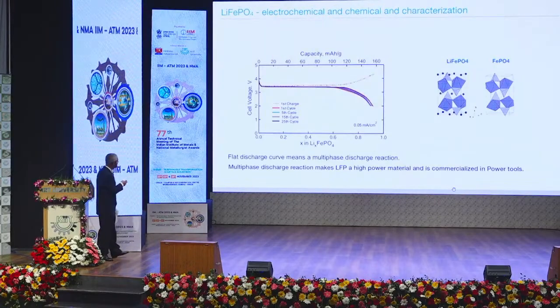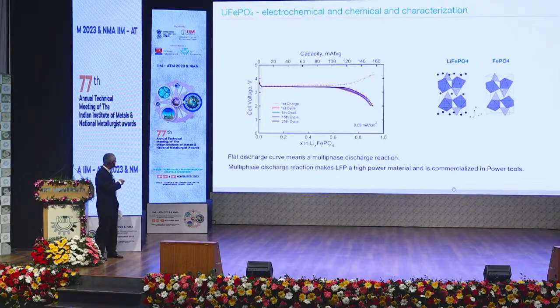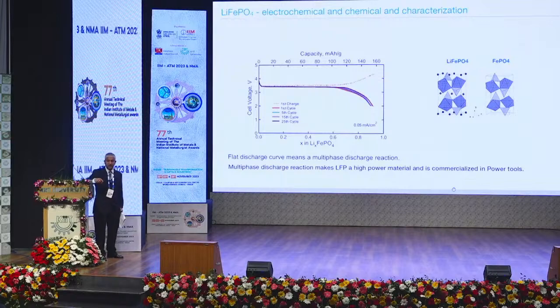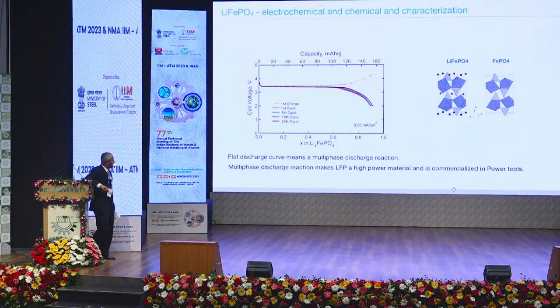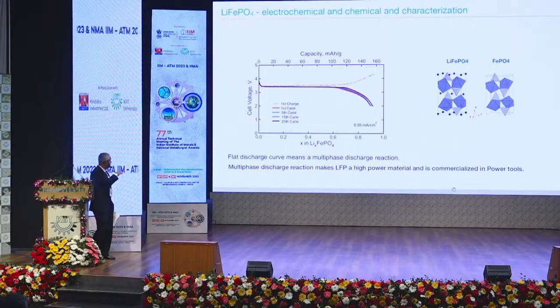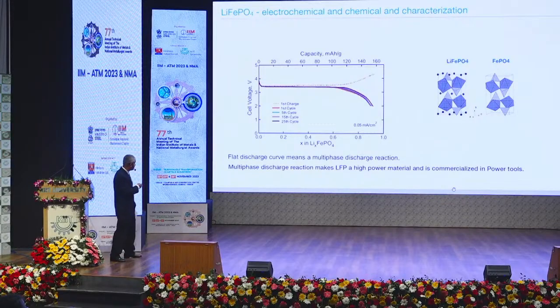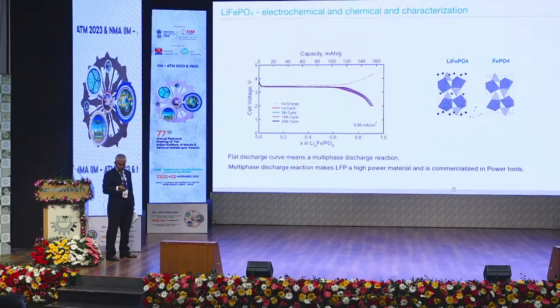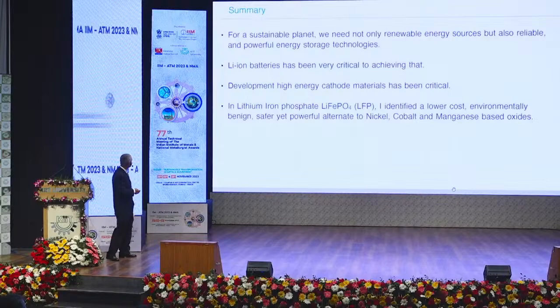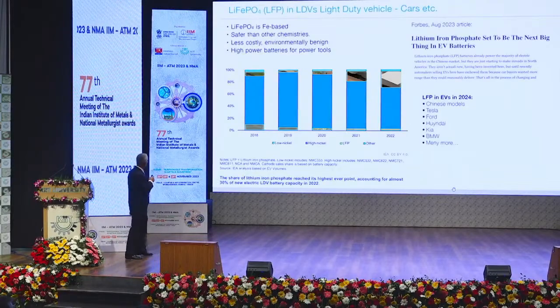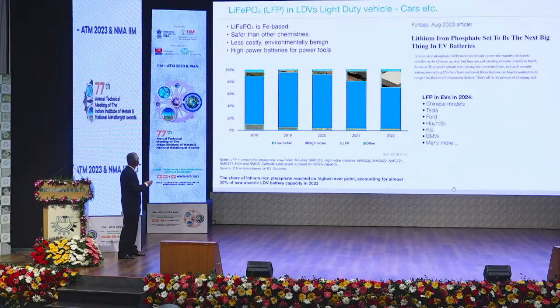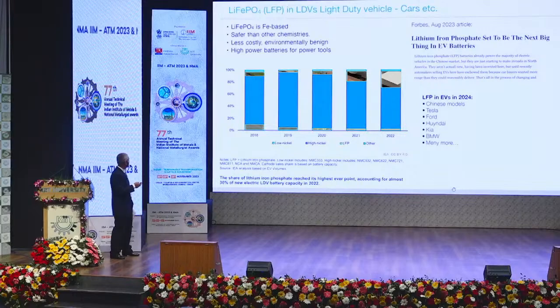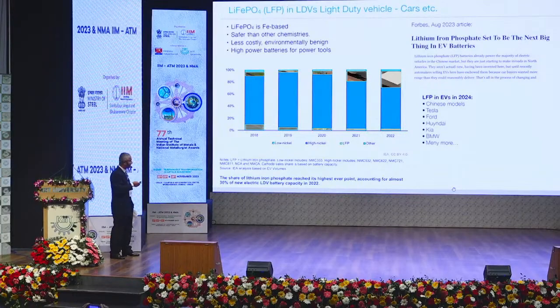What we showed is that lithium iron phosphate can be charged and discharged at 3.5 volts. We could extract the lithium out of the lithium iron phosphate, resulting in iron phosphate, and that slight volume change while we extract resulted in a multi-phase discharge reaction. Actually, the multi-phase discharge reaction is not bad because it was first commercialized in power tools. So lithium iron phosphate is iron-based, safer than other chemistries, less costly, environmentally benign, and high power for power tools.